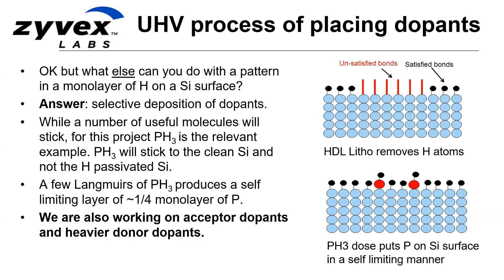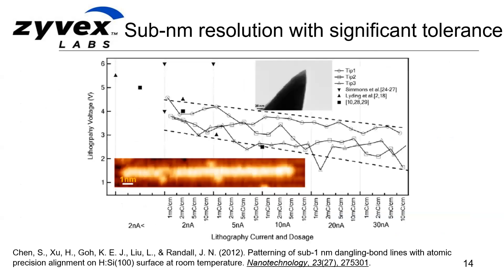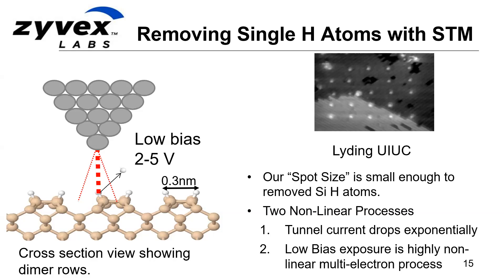Other dopant atoms are coming along as well. Combined with low-temperature epitaxy, this is a very effective way of making quantum devices that we and our collaborators are pursuing. The process is also very robust: not only are small variations in tip position accepted, but large variations in dose, current, and voltage all still produce these 7-nanometer features. We can even — though it's a bit harder — target and remove a single specific hydrogen atom, breaking that silicon-hydrogen bond. Some earlier work by Joe Lyding demonstrated an array of individually removed hydrogen atoms from the surface of a silicon-100 chip.